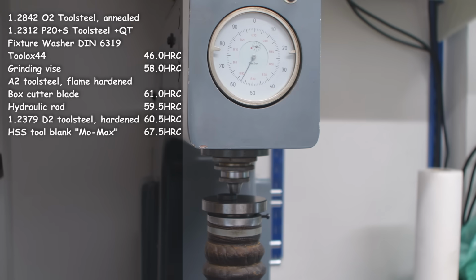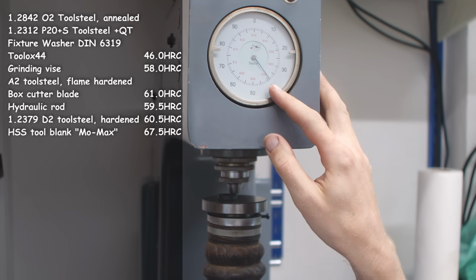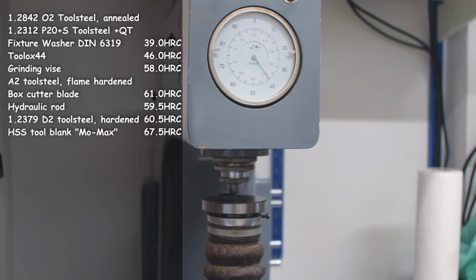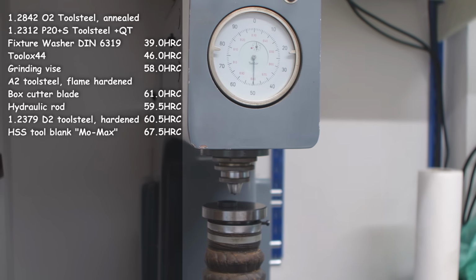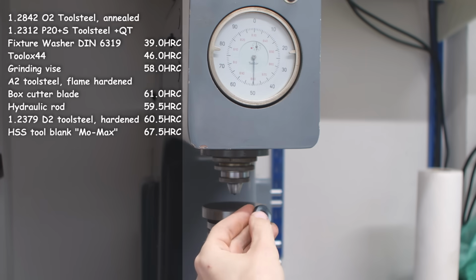Some people call these washers hardened. They are not really hardened, but whatever. They are usually a very decent heat treat. So the needle settles out. This one is 39 Rockwell C, which is far from hardened, but also it's a decent toughness.